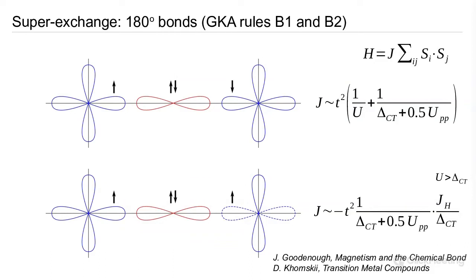Our exchange parameter becomes slightly more complex, but all I wanted to point out is that still it's proportional to this hopping t squared. We've got 1 over U in here. The Coulomb repulsion is against the process, and then what turns up is this delta CT, which is essentially the charge transfer gap, which is the energy cost of moving the electron from a d orbital into the oxygen. So this wasn't present in the previous case.